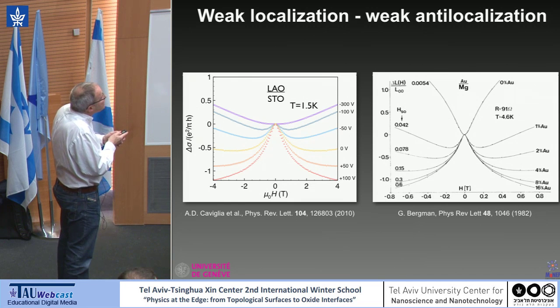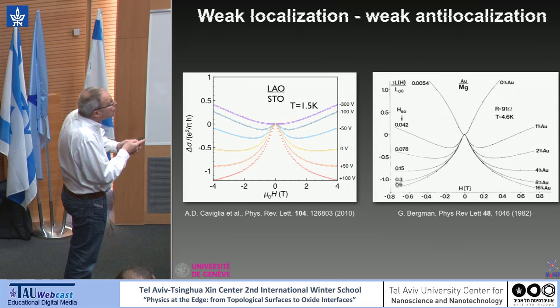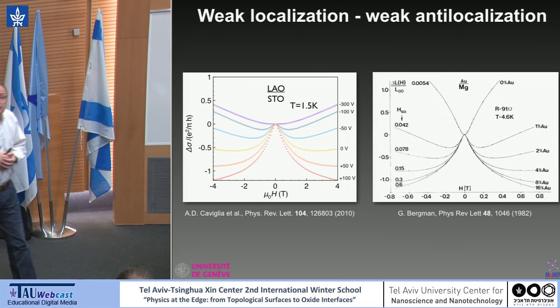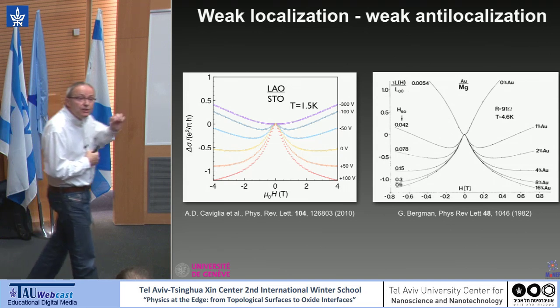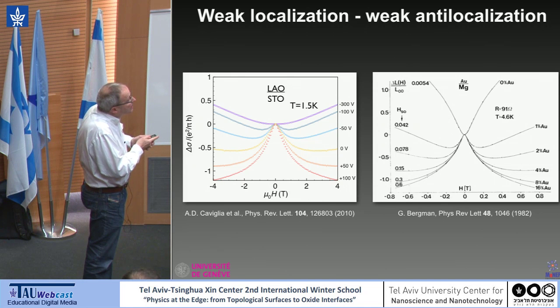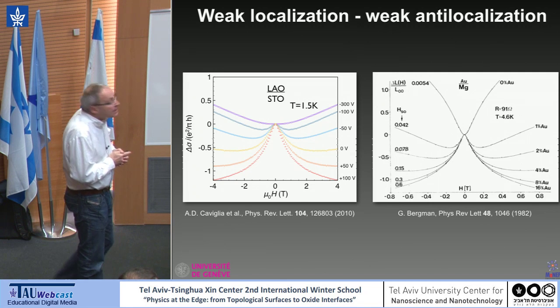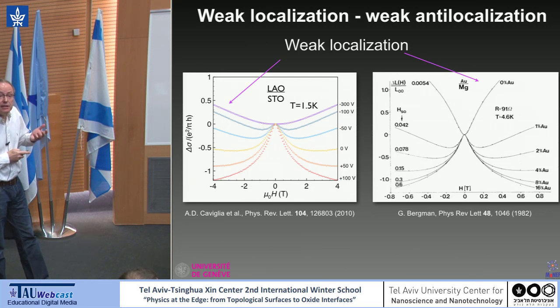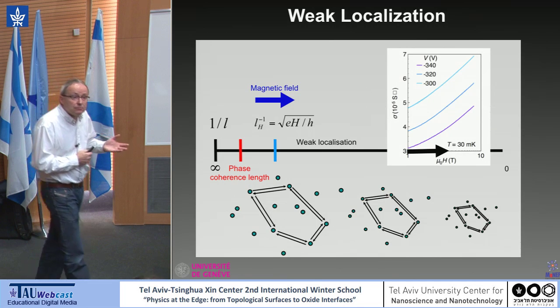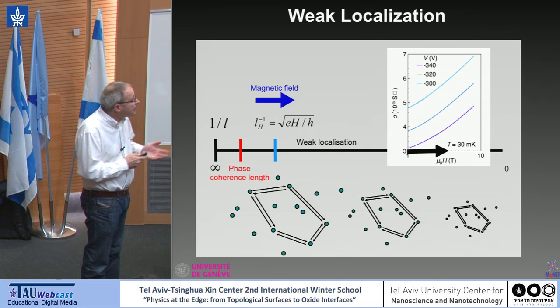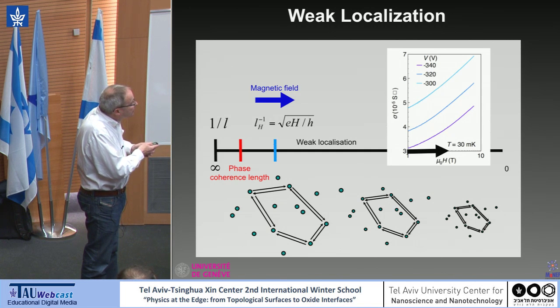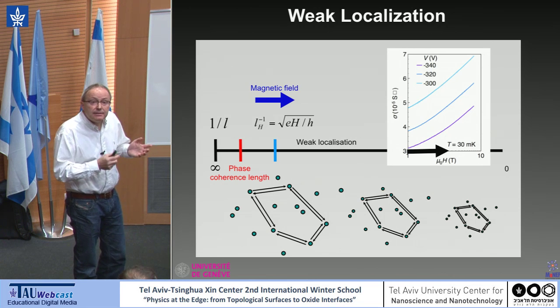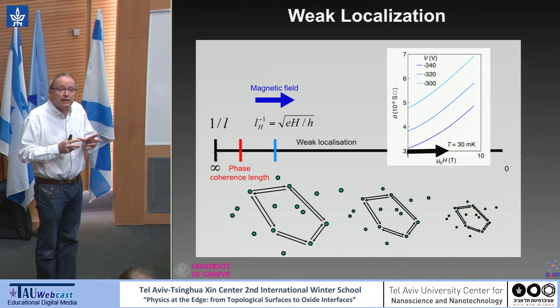And what we see is a conductance which is increasing as you increase magnetic field, and the scale is e squared over pi h. What I'm showing here are very famous data from Bergmann, who was studying at the time 2D conduction in magnesium. If you take a pure magnesium film, you see this same effect, which is shown here. This is weak localization. This weak localization is a quantum correction to the conductivity that you observe at low temperature, and which is due to electronic interference around closed paths. And these interferences are leading to localization.